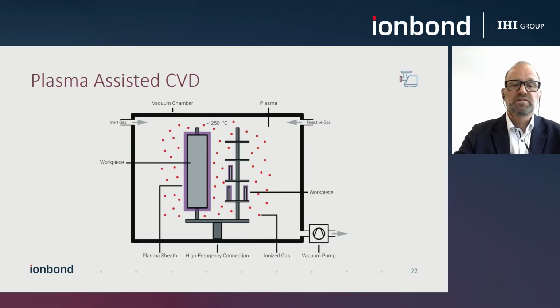And then by radio frequency, which is fed into the goods, as you can see from below, we can start a plasma sheath, which is around the goods to be coated. And in this plasma sheath, a chemical or a physical reaction is taking place. And the carbon, which is filled into the chamber, is then transformed into graphite and diamond atoms. And this mixture of graphite and diamond atoms then is creating a coating, which we call DLC, diamond-like carbon, which is an extremely smooth, amorphous, and very hard coating. And we can do this at relatively low temperatures, and the results are really outstanding.